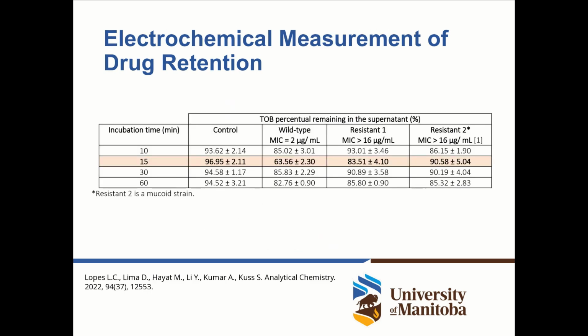Of course, we don't carry out these studies just once, but we are doing a large analytical investigation here. The plot that you have just seen is one experiment that corresponds to the highlighted section here for 15 minutes of incubation. But we also investigated longer incubation times, where we see that this difference in current response is not as pronounced. We validated this with fluorescent microscopy, because these cells are just too stressed. They are breaking apart, and tobramycin is given back into the solution before centrifugation if the incubation time is too long. So we see here that 15 minutes of incubation is very suitable to not just detect a drug susceptibility by electrochemistry, but also to differentiate not only between susceptible and resistant organisms, but also between different degrees of resistance.